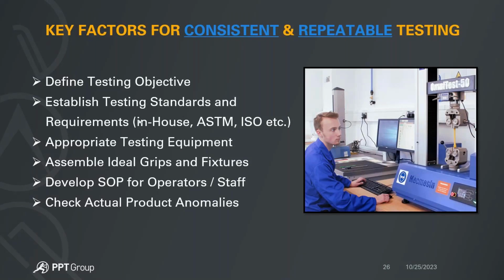Whether you're at the point of R&D, QC, production, or supplier verification, you need to know what the objective is. What are you looking for in the test? And that usually means you know what the product is. I'm going to take your 20-ounce bottle here, and we'll say, in our 20-ounce PET bottle, which holds water or your favorite beverage, we expect it to meet a minimum threshold of 30 pounds if we applied a top load to it. Or if we compressed it to a quarter of an inch in deflection, we should see a minimum of 20 pounds. If we see something higher, great, our bottle is strong enough. If we see something lower, there's a problem.